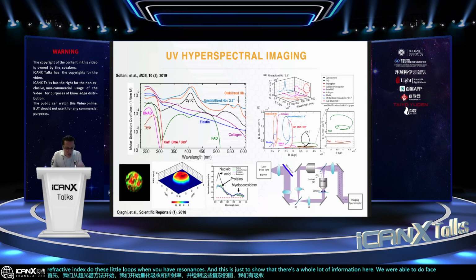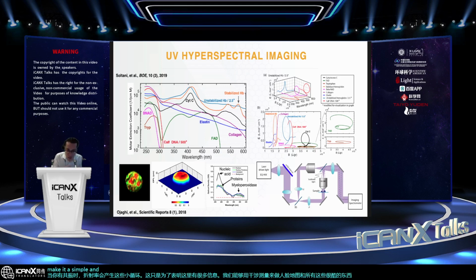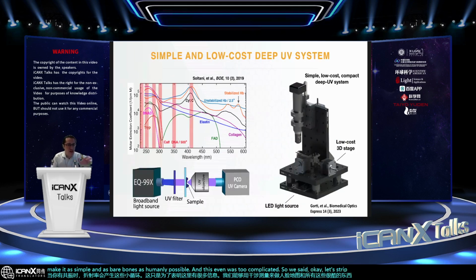But as we were moving forward with this technology, we really wanted to make it as simple and as bare bones as humanly possible. And this even was too complicated. So we said, okay, let's strip all the complexity and just simply do transmission-based absorption imaging, where you can have a broadband light source and UV filters, or a bunch of LED light sources, and then just a microscope in key wavelength regions. And by the way, this paper was just published this past year, where we show that you can make these systems with very precise 3D stages for less than $5,000. So this is compact and low cost.